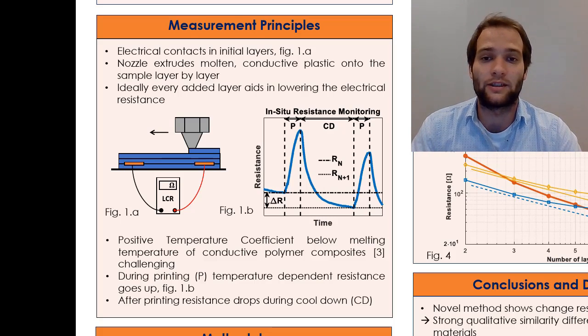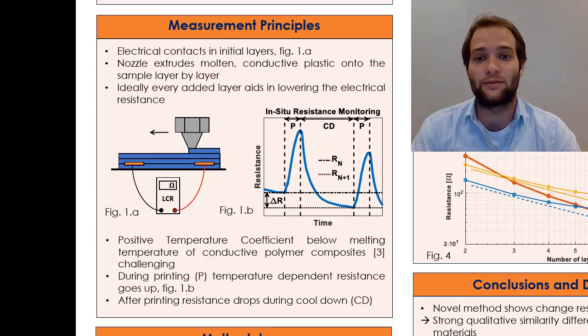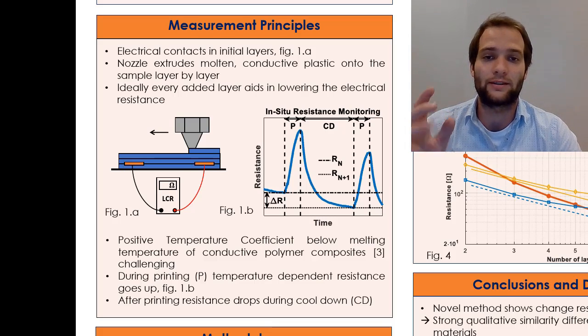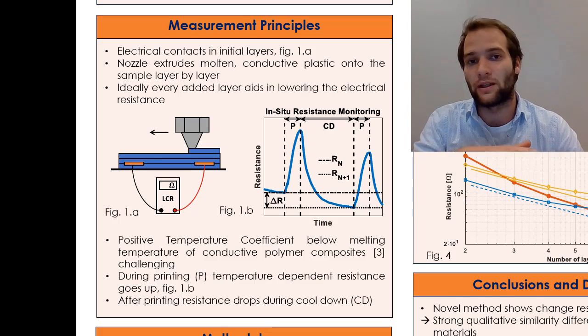One of the challenges is the positive temperature coefficient of conductive polymer composites. Since below the melting temperature of these materials, they have a positive temperature coefficient. So when the temperature goes up, the resistance goes up. So during the print phase, as you can see in the figure, the resistance goes up. And then after cooling down, during the cool down phase, you can see the resistance going down to a lower value.